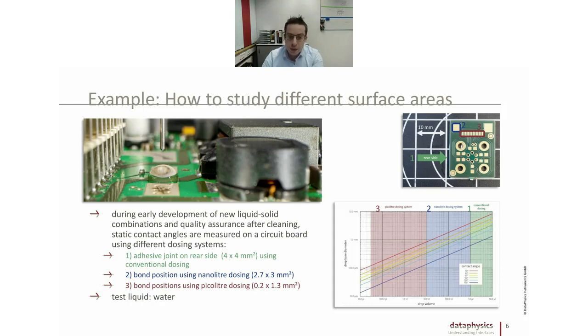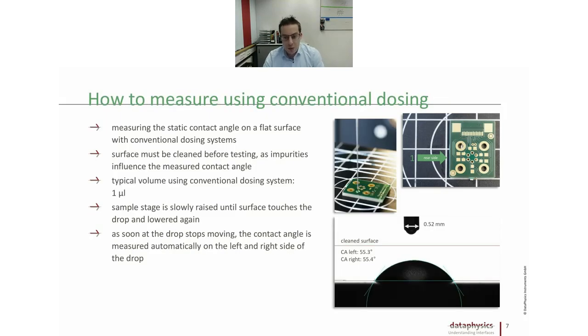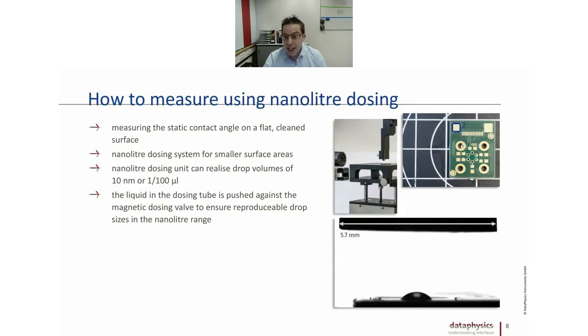And I want to show you this now with a couple of practical pictures. Let me go one slide further. So in this example, we are measuring with a simple needle-based system. This is the standard system for contact angle analysis on this PCB board. Volume is around 1 microliter, and this is the droplet's picture on the surface. Very simple, possible to see from the side, contact angle around 55 degrees. What happens if we want to measure in these areas, area 2, for example? Then we should change our dosing system and go for a nanoliter dosing system.